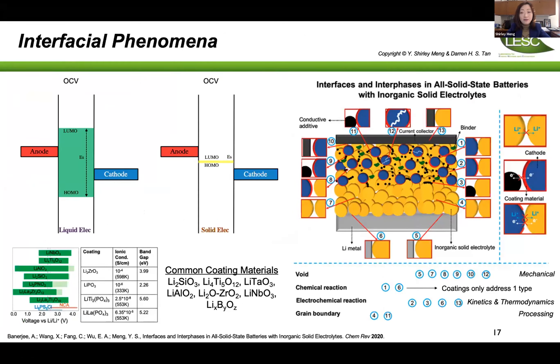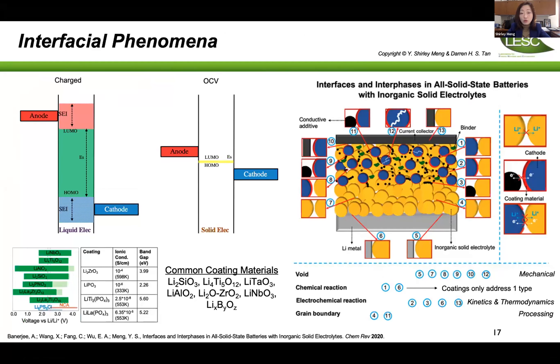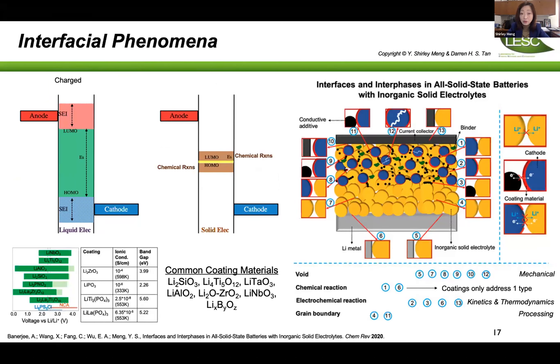From a scientific perspective, solid-state is a very nice platform. In liquid systems, you only have an unstable surface when you start to sweep the voltage. In solid-state, the situation is completely different: if you have a sulfide-based electrolyte and an oxide cathode, the interface when you put the two solid materials together is already chemically unstable. That's why Dr. Sun showed so many coating strategies including ALD — those interfaces must be perfectly protected against chemical instability. And once chemical stability is achieved, you still have to deal with the electrochemical SEI problem when sweeping voltage.